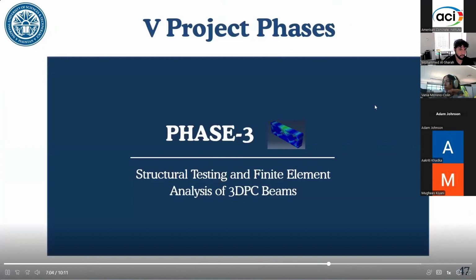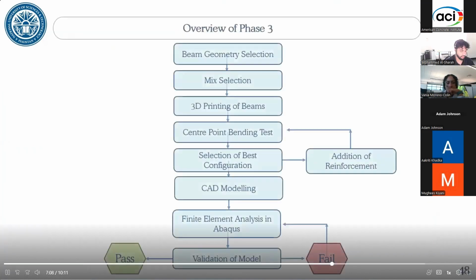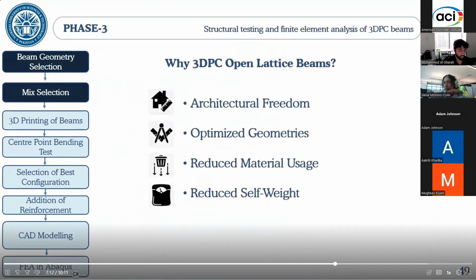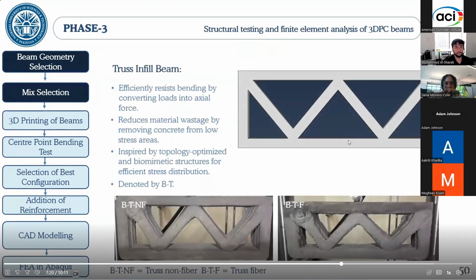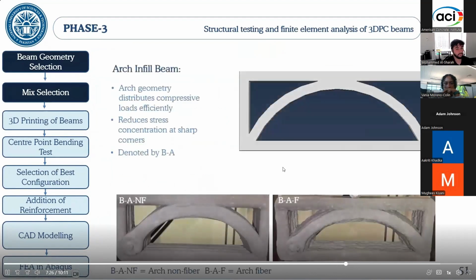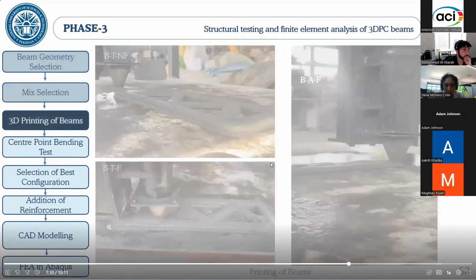So for the third and final phase, we wanted to test 3D PC beams both experimentally and numerically. Here is the overview of our third phase. As mentioned earlier, 3DPC allows us full architectural freedom and to print optimized geometries whilst reducing the material usage and the self-weight. For this reason, we chose 2 geometries, the first one being the truss infill beam, which reduces material usage at low stress points, and the second being the arch infill beam, which efficiently distributes compressive loads.